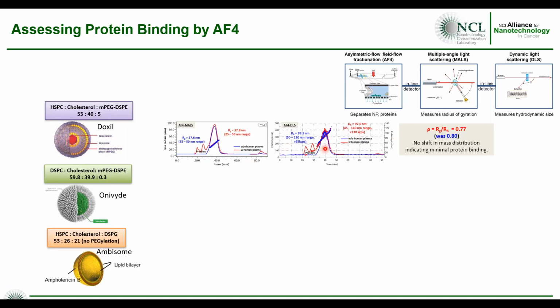This is the DLS trace. So from both of these, you can calculate this shape factor, defined as Rg over Rh, and you can calculate this before and after plasma incubation. In this case, they're roughly the same. So this implies minimal protein binding.